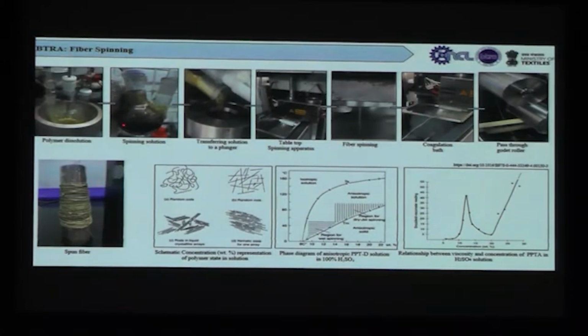The next challenge after the polymer synthesis is the spinning. This is an infusible polymer. It does not melt, so melt spinning is not possible. It has to be done in solution state. And as I mentioned, since it does not dissolve in normal organic solvents, this is dissolved in sulfuric acid, that too concentrated sulfuric acid and oleum.